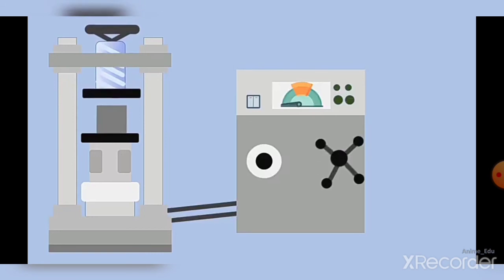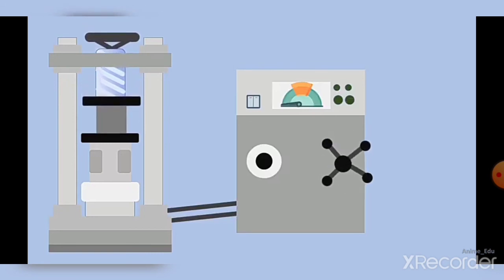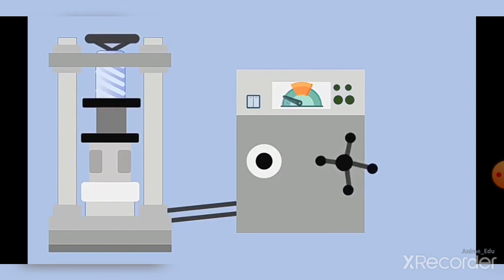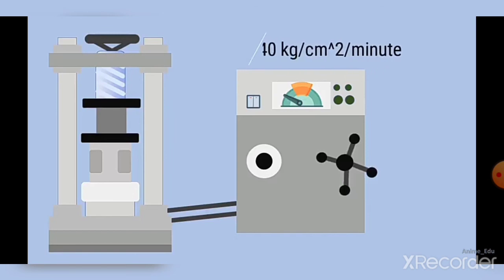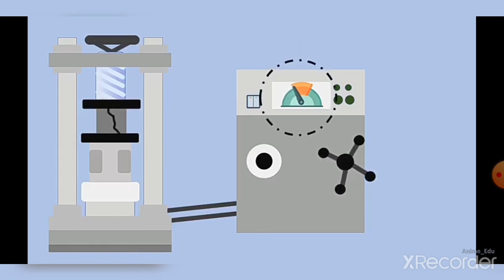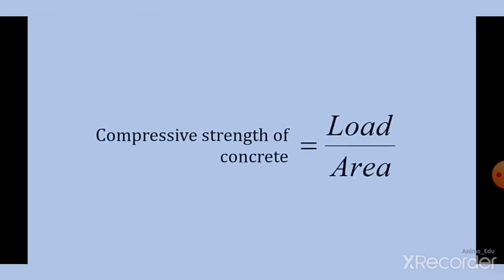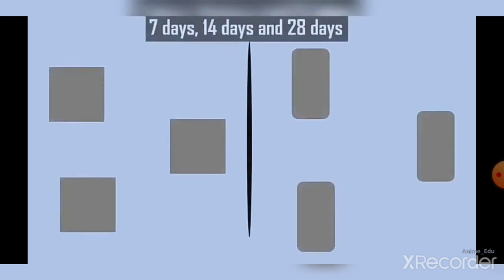The instrument is adjusted such that the plate touches the top surface of the specimen. The load is applied gradually over the specimen at the rate of 140 kg per centimeter square per minute. The load at which the specimen fails is noted. Thus, the characteristic compressive strength is calculated from the ratio of load and the area. The test is generally done with the help of 3 specimens and tested for 7 days, 14 days and 28 days.